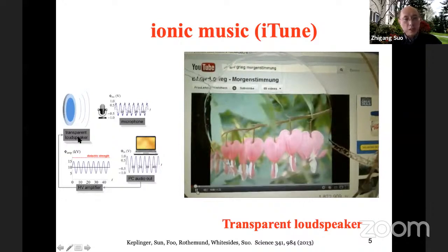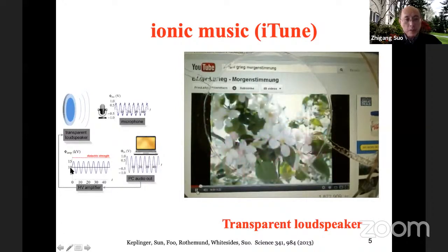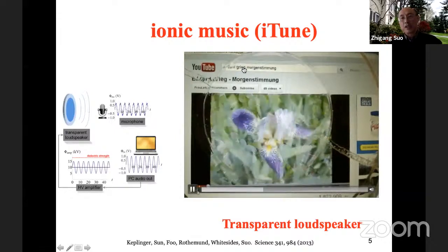So what it does is we have this device. This device was fed, using a computer, a voltage signal, and the voltage caused the membrane to vibrate. Vibration generates sound, and you hear the sound. We record the sound, and you can see this loudspeaker - there's a piece of hydrogel elastomer that's fully transparent. Beautiful piece of device, and the musical quality is pretty good. We don't know enough about sound quality to test it properly, but it's good enough for us.